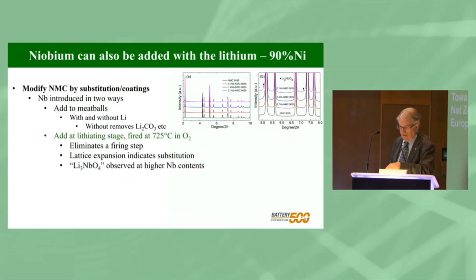What our second thing to do was when we discussed this with our sponsors, DOE, they said, you've taken the meatballs. They've been fired once, you're now going to put niobium on them and you're going to fire it again. That's an expensive second step. So what we then did was made our own layered oxides. We got the precursor, which is the hydroxide. With the hydroxide, you then fire it up with, say, lithium carbonate or lithium hydroxide. We added a niobium at that stage. So we didn't add the extra step.